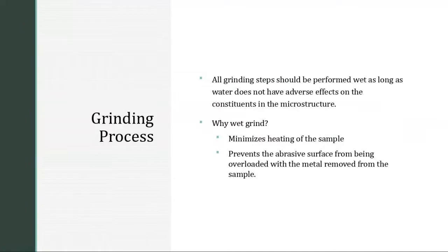As we look through, all the grinding steps should be performed wet, as long as the water doesn't have any adverse effects on the constituents in the microstructure. Some metals don't like water, so you might have to grind with an ethanol or glycol-based lubricant instead of water. But those would be specified depending on your sample preparation process. For instance, if you wanted to polish magnesium, magnesium doesn't like water, so you would use a glycol or alcohol process instead.